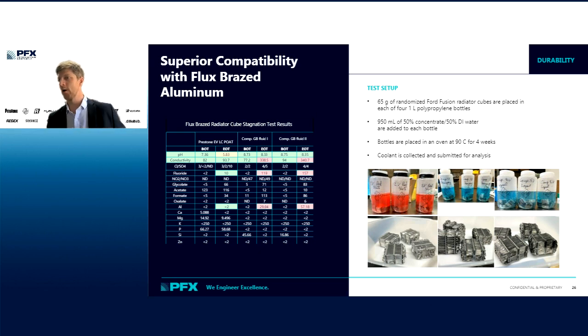So what we do is we run an accelerated test. We call it a radiator cube stagnation test. We cut up the radiator from a light-duty vehicle into cubes. We weigh these cubes, submerge them in the fluid. These are cooked at 90 degrees Celsius for 4 weeks, and we take the coolant out. We analyze the coolants, and we visually analyze these samples.